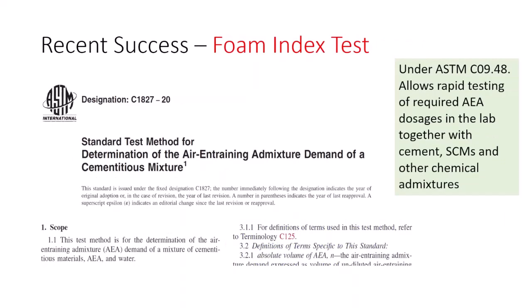One of the things we need is better performance tests, and something that has been developed with a number of people, and Larry Sutter got this through the system, was a foam index test. It's not a new test, but it was originally applied to evaluate loss on ignition in fly ashes, but it can be, I chair a committee on performance of cementitious systems with chemical admixtures, like looking at the whole binder, and this test can be used to evaluate whether you're going to have air entraining issues with a combination of your chemical admixtures and cementitious materials.